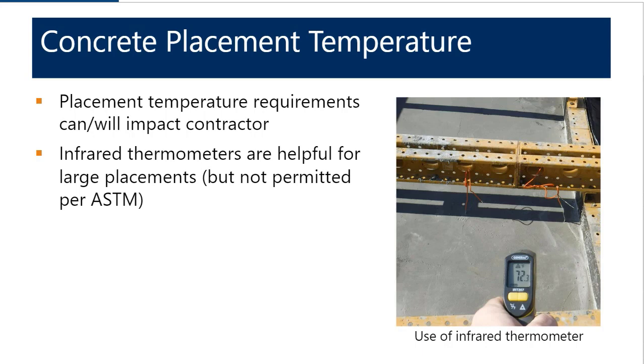Infrared thermometers are very helpful for monitoring the placement temperature of concrete. So that's something that can be used for larger placements where the service is very high, meaning up to 1,000 yards an hour. It may not be practical or efficient to use a traditional temperature measuring device on the plastic concrete, and it may be easier to use an IR or infrared thermometer as the concrete is coming out of the truck.